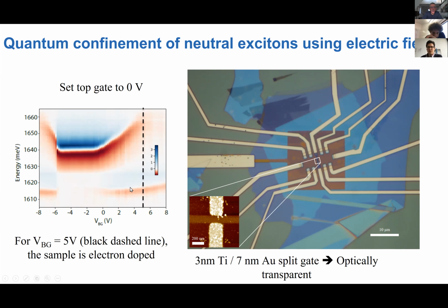So this is the analog of the measurements I have shown you before. You see some problems, for example, hole doping is very non-trivial. It increases abruptly and then levels off. This is a generic problem with molybdenum-based materials where the P contact doesn't simply work very well. If you look at the electron side, it's better.